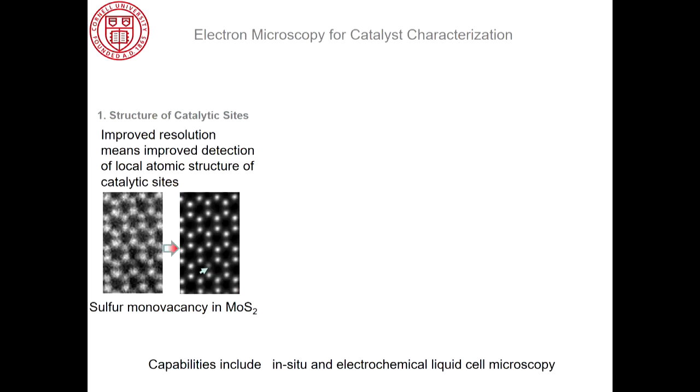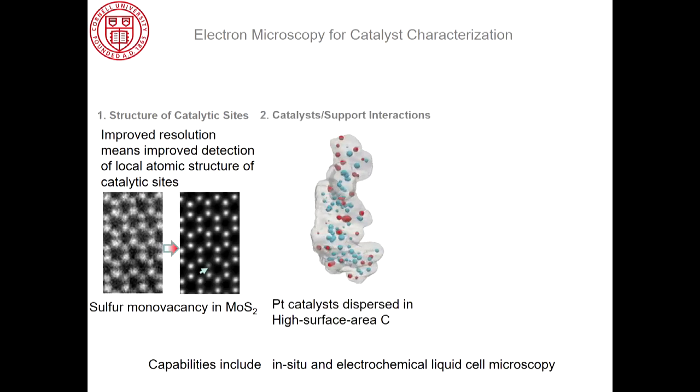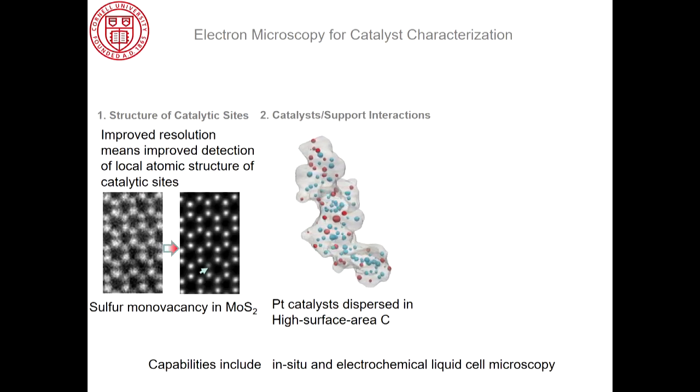So where are we at to about now? Certainly the new detector using a method called ptychography has improved our resolution, so that now you can pick up defects very nicely. This is a monolayer of MoS2, one atom thick except for two sulfurs, and over here I'm missing a single sulfur atom, and it jumps out beautifully. So we can see individual defects if you're trying to think about catalysis. We're obviously able to image things in 3D.